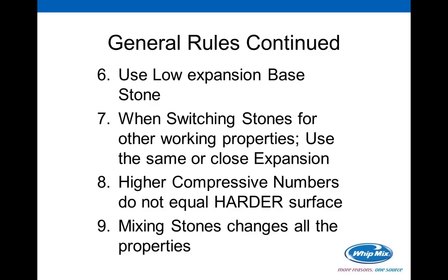Our next question is, what happens to expansion or other properties if you do not use the correct water-powder ratio? I believe you might have already answered this one, but I know it's a really important thing to go over again. We hear this a lot, and the reality is that within 1 or 2 milliliters per 100 grams, on either side of that number, you're not going to get a real change in your expansion. You will get a change in your other properties, however. You're going to get a change in the compressive strength, either up or down. Too much water, lower compressive strength. You shorten the amount of water, you're going to get higher compressive strength.